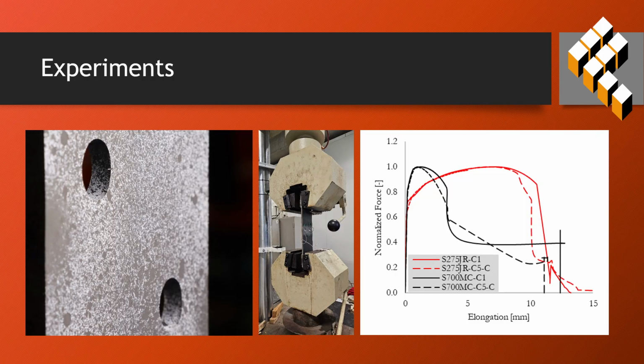The experiments are conducted on specimens made of different steel grades with 4-hole configurations. The specimens are first subjected to a pre-cracking procedure and then tested under tensile loading. For tests conducted at low temperatures, the specimens are first cooled prior to the test and then tested in room condition, where the temperature is monitored by a thermocouple.